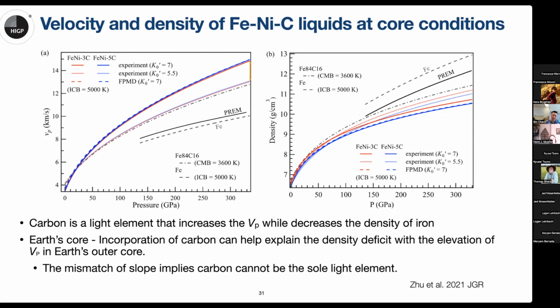If we use the compressibility and also the density of this iron nickel carbon liquid, then we can calculate the compression wave velocity. As we can see, that is higher than the PREM compression wave velocity of pure iron. And in terms of the density, it is actually much lower than the PREM values, and it also has a shallower slope than the PREM values. So this mismatch of the slope and the absolute value implies that carbon cannot be the sole light element in the Earth's outer core. So there should be some other light element that can really make the velocity and the density profile much better.